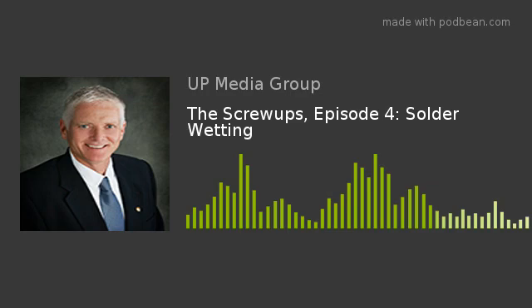So de-wetting is where wetting occurred and then it retreated and it came back from whatever it was wetting to for a variety of reasons. But the primary reason is usually exhaustion of the flux. So flux does a couple of different things. It not only breaks down the oxides and removes grease and oils to permit the intermetallics to form, but it also has what we call blanketing agents in it that prevent the surface from reoxidizing. So if you exhaust all of that, reoxidation occurs because, as I mentioned earlier, throwing heat at it, you get an oxide layer, and then eventually there's just not enough blanketing agent or activator left, and the solder will retreat from where it had originally wetted.